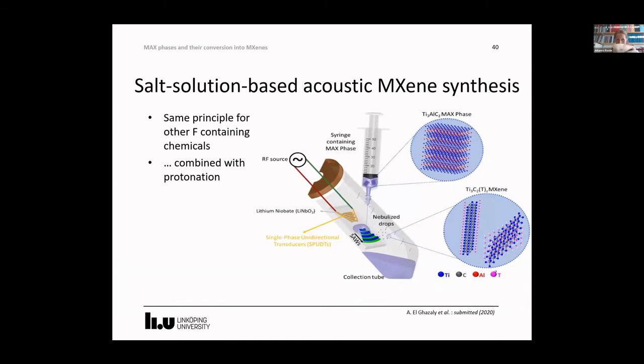In other words, the proton formation combined with the fluorine ions will form localized HF, which works as a local etchant for the MXene synthesis. The concentrations of chemicals can also likely be tuned so that the localized HF formed in situ is completely consumed in the process.